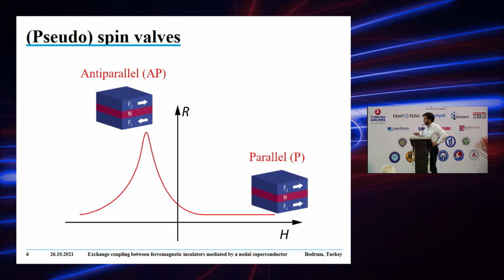This is actually a pseudo spin valve, because as you can see, there are two ferromagnets sandwiching a normal metal. In an actual spin valve, one of the two ferromagnets is pinned by an antiferromagnet grown underneath. So you can switch independently the orientation of the magnetizations of the two ferromagnetic layers. You go from a case where both are parallel at high fields and the resistance is low. Then when you start sweeping the field in the negative direction, the soft one will switch antiparallel compared to the previous one, and this gives you an increase in resistance.